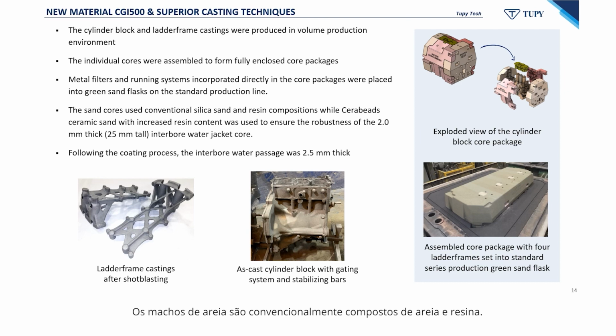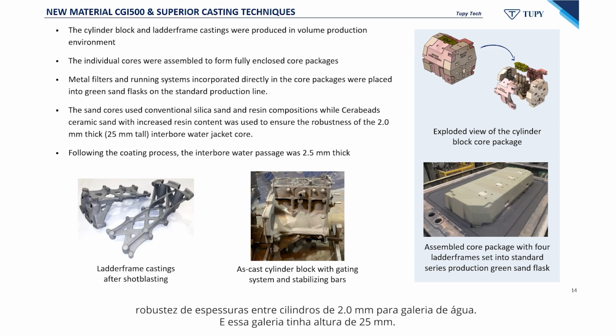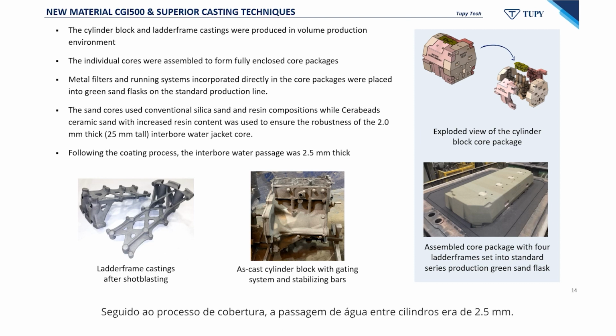The sand cores used conventional silica and resin compositions. In comparison to that, cerabeads ceramic with increased resin content was used to ensure the robustness of the 2 mm thick interbore water jacket core, and this jacket core had a height of 25 mm. Following the coating process, the interbore water passage was 2.5 mm thick.